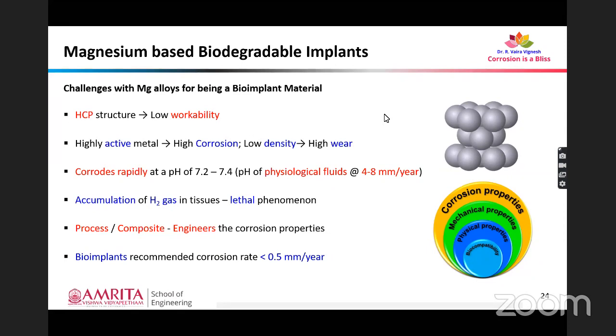So in the normal human body environment that is rich in chloride ions and has a pH of 7.2 to 7.4, magnesium corrodes at a rate of 4 to 8 mm per year. So if we have such a high corrosion rate, that will result in formation of hydrogen gas in the tissues, and that is a lethal phenomenon. So we have to do a process or prepare a composite to engineer the corrosion property of magnesium alloy so that we achieve a low corrosion rate.